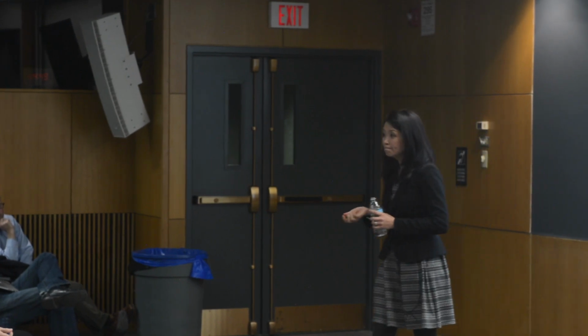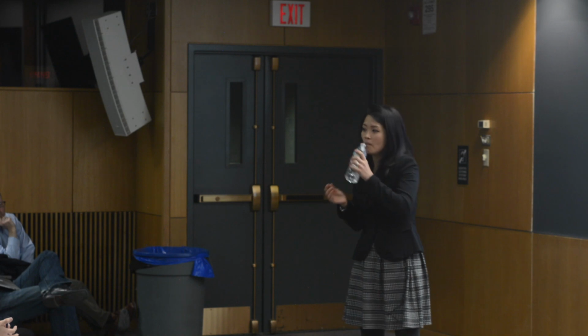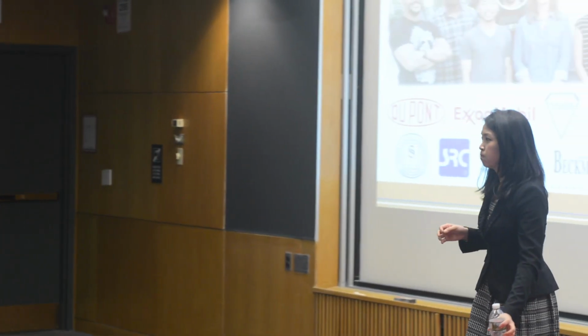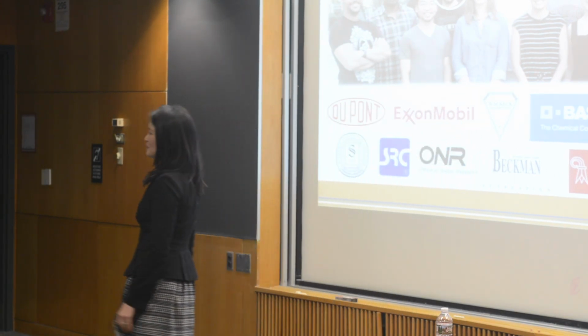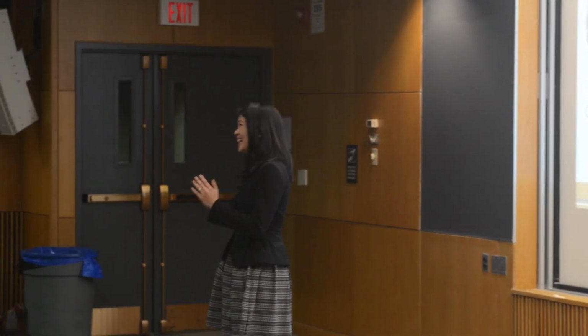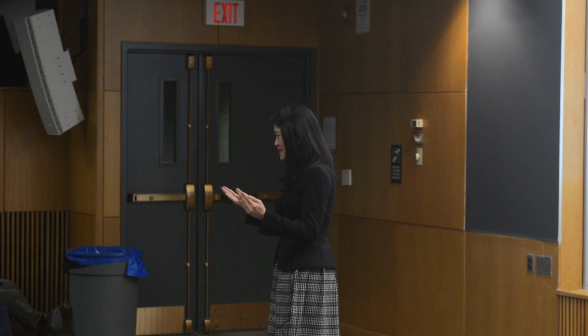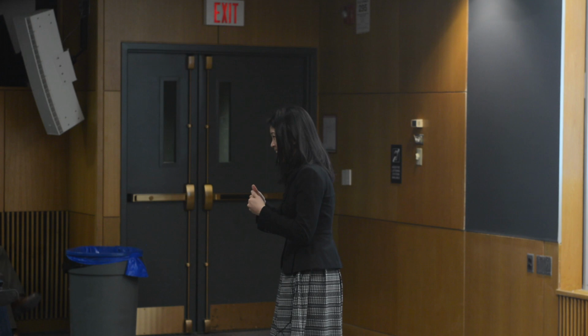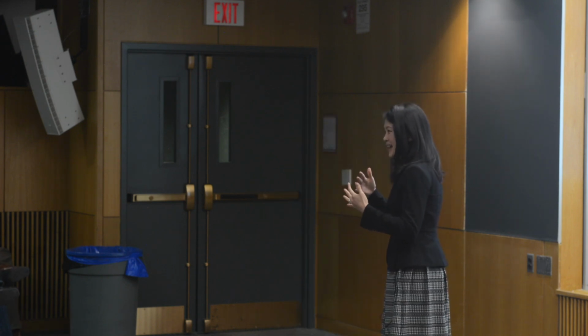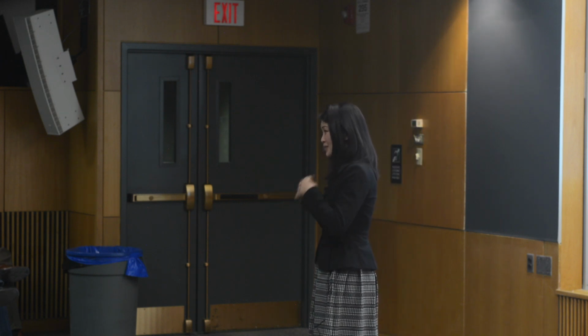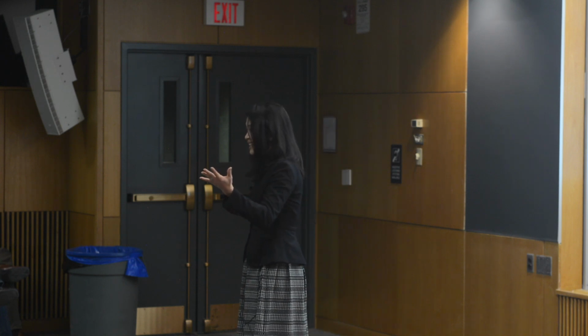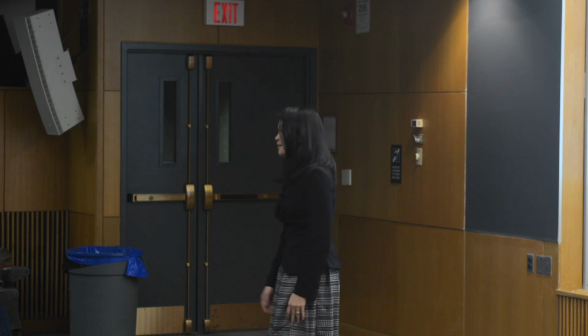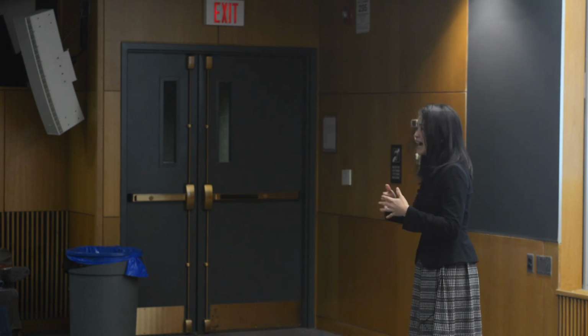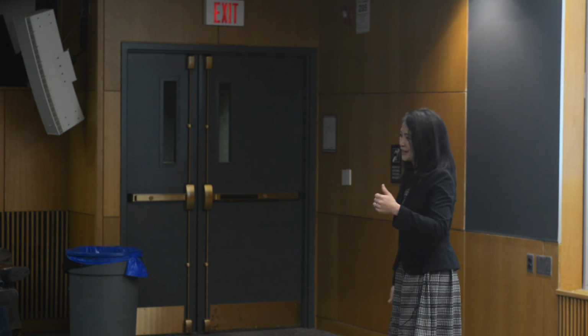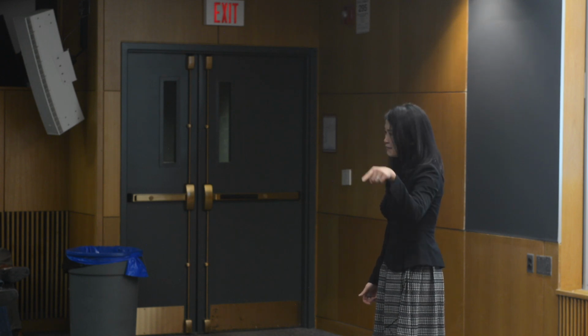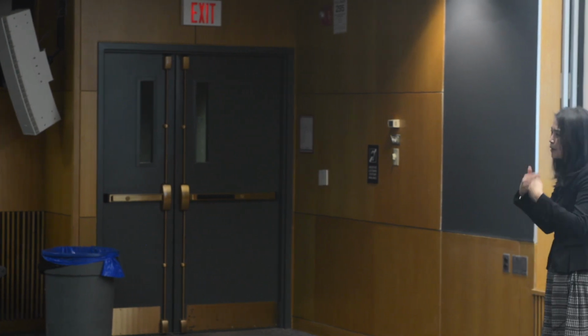You mostly talked about the kinetic aspect, right? So is there any dynamic implication in some of your studies, for example, that interlayer contacts can be altered by some process, such as spin casting or anything? Yeah, well, that's the question, right? Ideally, what would be nice is if you can unlock it when you want to unlock it, and then lock it back when you want the structure to stay. And I think this heteroepitaxy templating could be a way to do that, right? So you lower the barrier to nucleation, you nucleate the phase. You get the phase that you can't usually get, and then once you get it, you convert everything to that phase, and then it stays there. So I think one needs to think about those kinds of parameters and how to tune external parameters. First one needs to figure out what you want and whether you can get there, and then design routes to getting to the endpoint. But that heteroepitaxy is sort of our beginning of thinking about this.